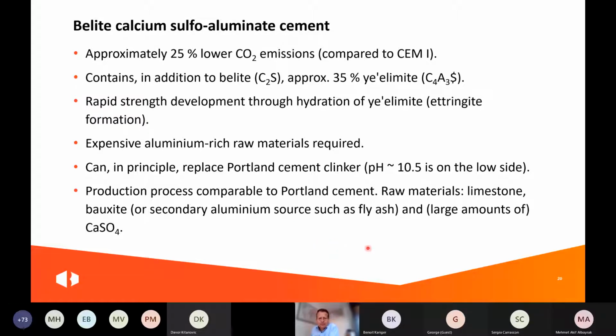But the downside, the pH is a little bit low with 10.5. So it will be more sensitive to carbonation, which is of course a risk for reinforced concrete. And due to the low pH, it is a bit more difficult to activate replacements of clinker like blast furnace slag and fly ash and calcined clay in the future. So you have to use it more or less in pure form, and then you have this 25% reduction compared to Portland cement.